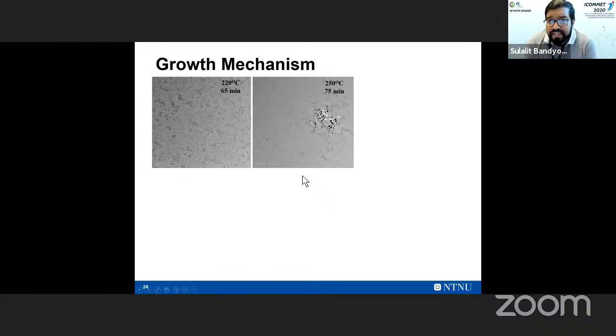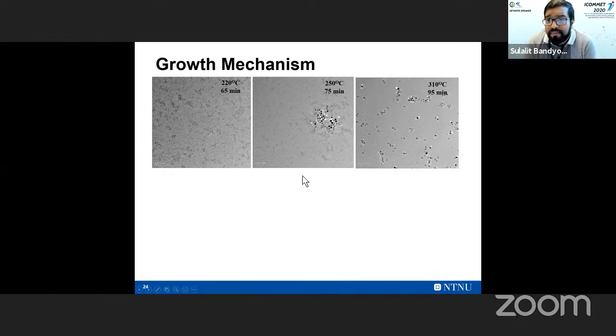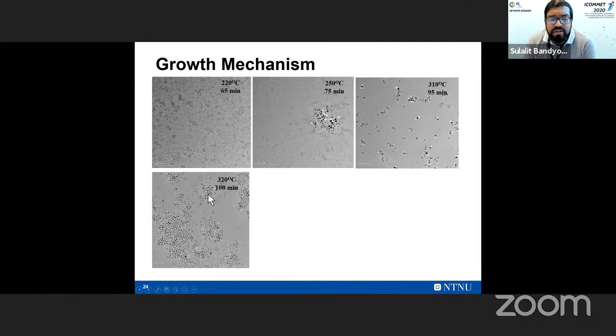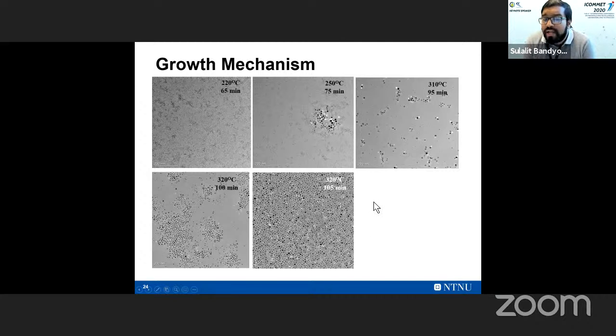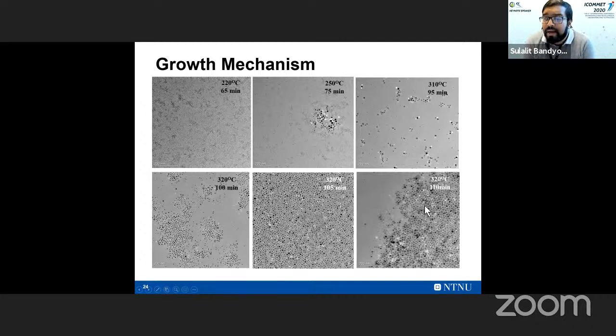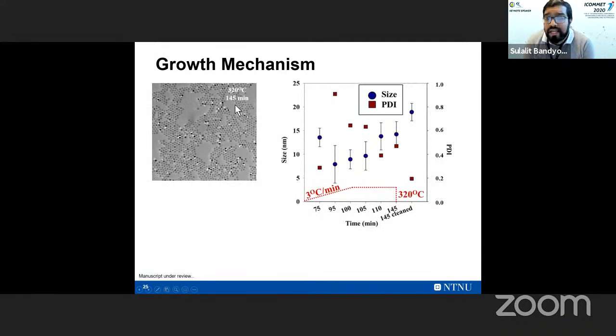On the other hand, if you look at the growth mechanism, as I said also with the iron oxide nanoparticles, this is a time-based TEM imaging done. Initially, you can see some needles, and then the first particles form with needles still there. And then if you look at these particles, there are lots of small particles and big particles. So they are polydispersed. Slowly and steadily with reaction time, they become more and more monodispersed. The final population is around the size of 11 to 12 nanometers.